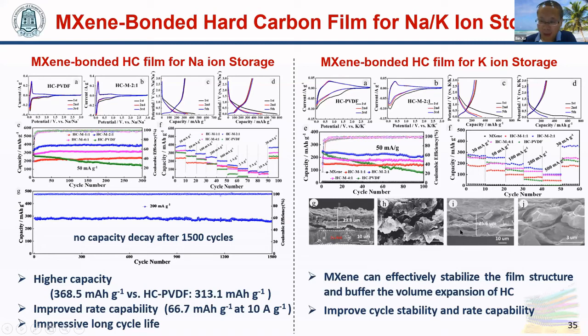For potassium ion batteries, we can see the capacities of PVDF bonded electrodes decay very quickly. But for the MXene bonded electrode, the cycle performance is very stable. So MXene can effectively stabilize the film structure and buffer the volume expansion of hard carbon.